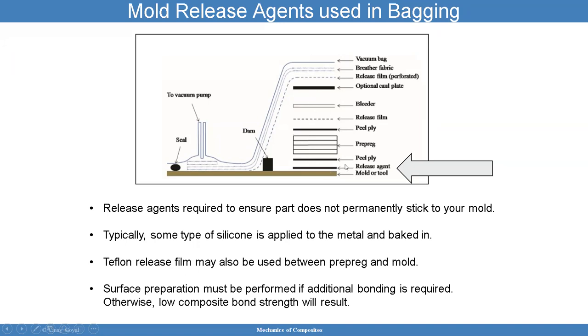But what I want to talk about is this release agent. This release agent is very important because it makes sure that the prepreg that you're curing does not glue onto the tooling. We don't want that. We don't want it to get stuck in the mold. Typically, some type of silicone is applied to the metal and baked in. Teflon release film may also be used between the prepreg and the mold. So that's typically the way it's done.